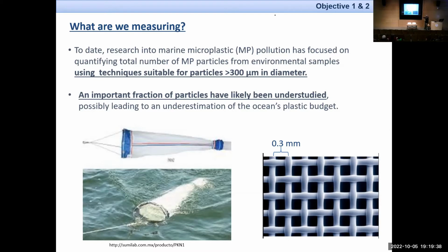So everything that is smaller than 0.3 millimeters goes through this net. So we cannot collect anything smaller than 0.3 millimeters in diameter. All those pieces of plastic are very, very small. They are not accountable by this type of study. They just collect particles bigger than this mesh. So we're missing a lot of the particles, a lot of that mass of plastic. So we think that this is one of the problems.